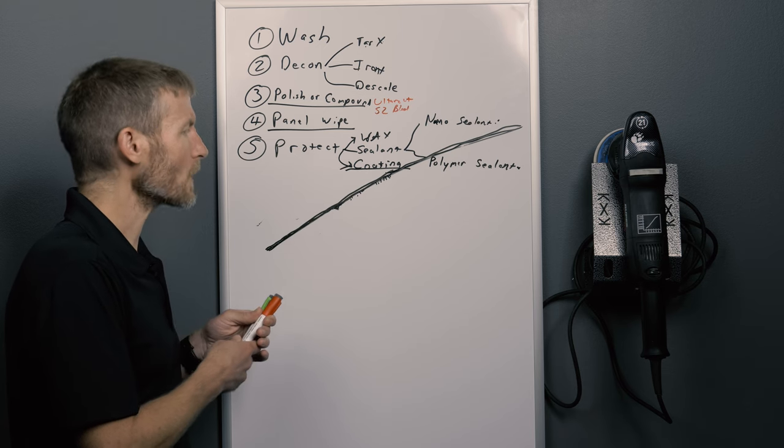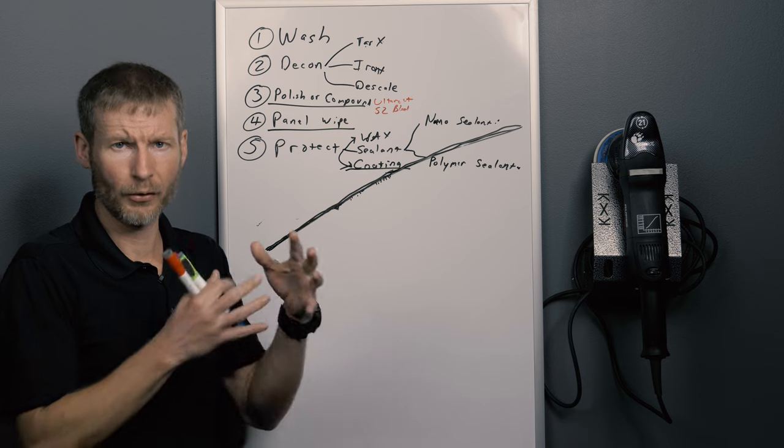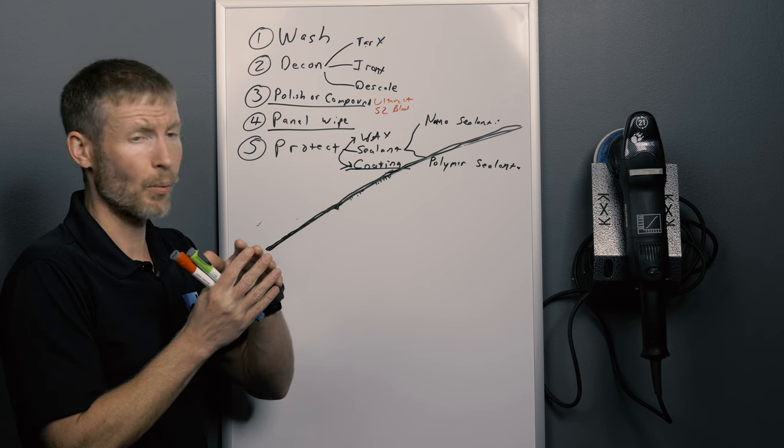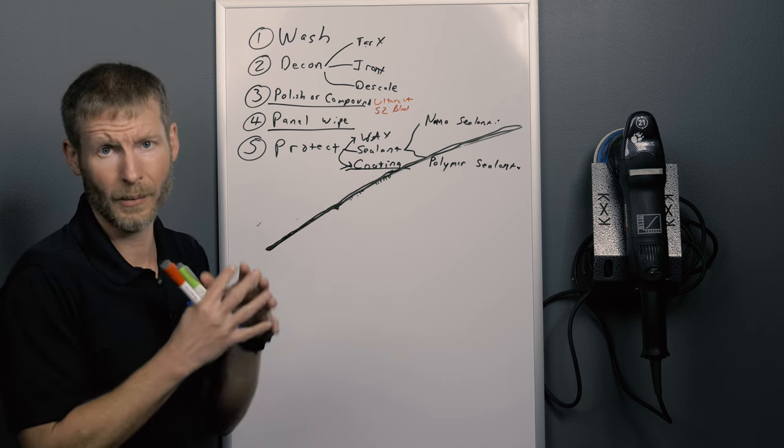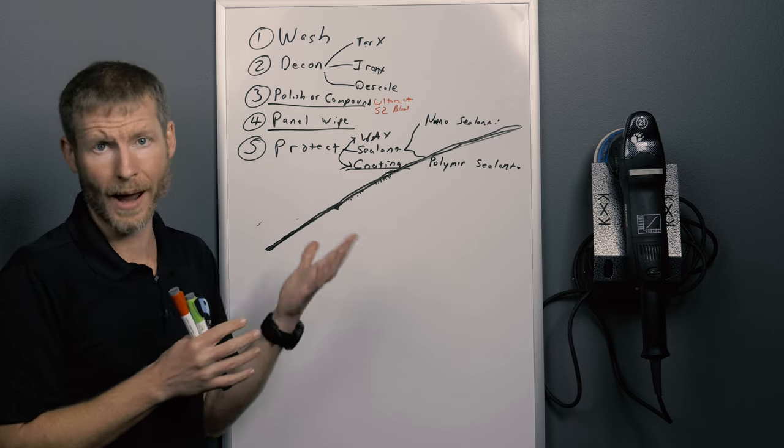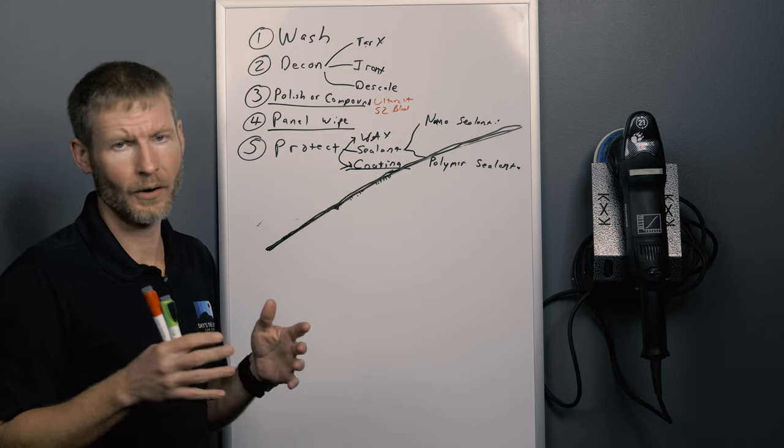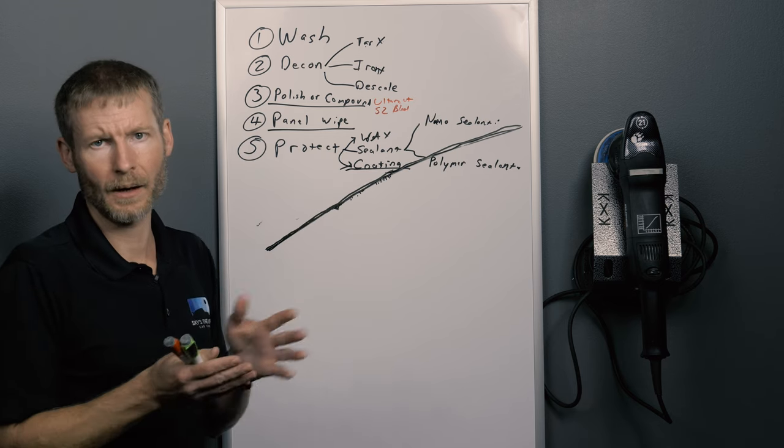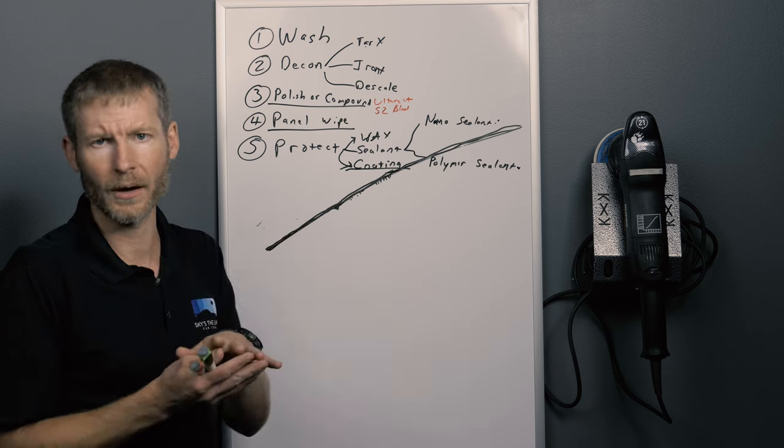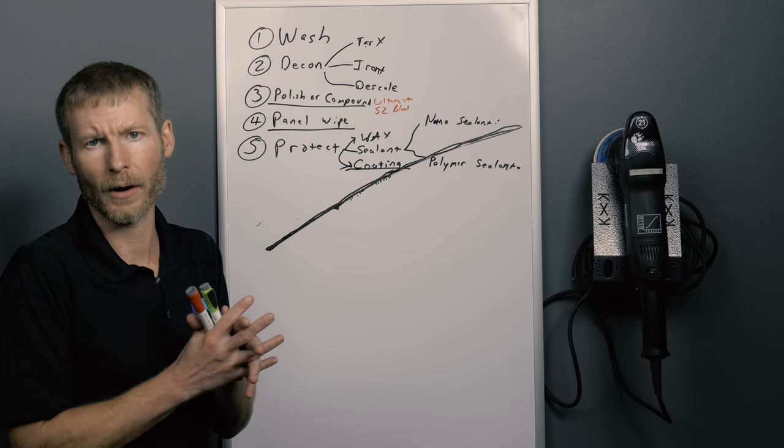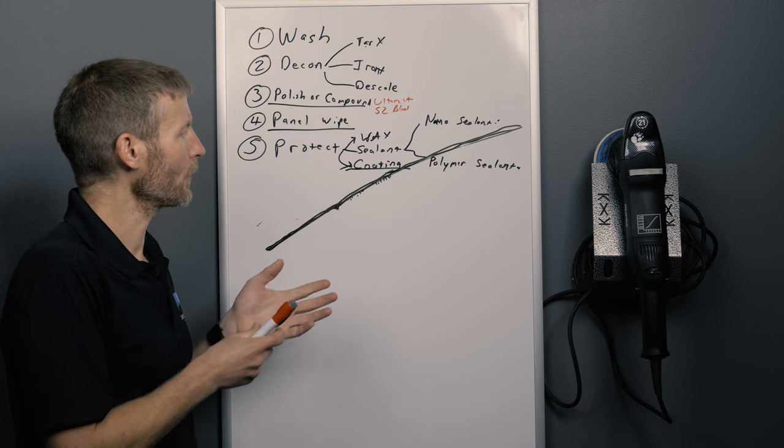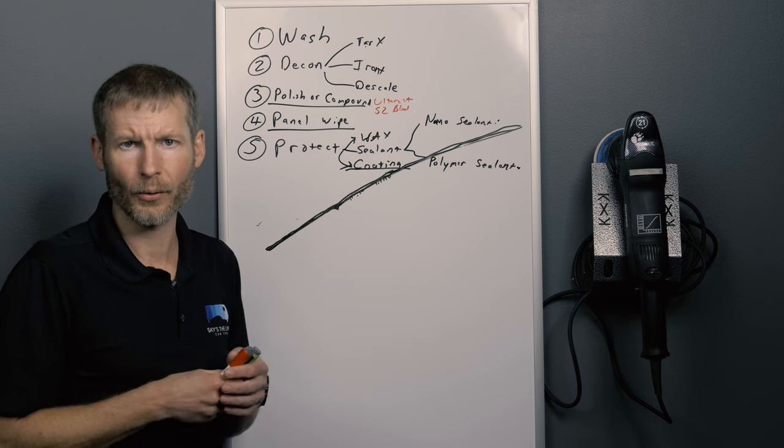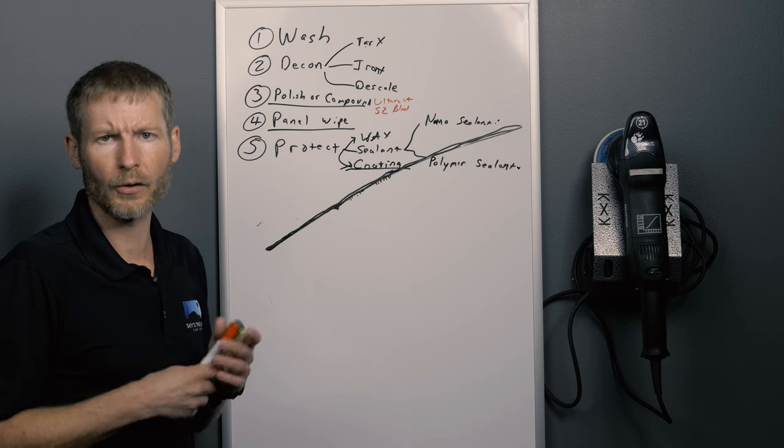So it's going to etch really, really bad and really easy. So over time, over 12 hours, 24 hours, especially if you IR cure it, it's going to become much more resistant and it's going to be a solid within 12 to 24 hours. Once it's a solid, then obviously it's going to be stronger. But it's still going to be those chains and the way that it's bonded to that paint is not going to be complete. In reality, it'll take weeks or months even for it to be at its full strength, at least weeks for it to be at its full strength. But it's going to be far stronger than a wax or a sealant pretty quick. Within three days, and this is, it all depends. Again, there's many variables in the world. The heat, the type of paint, the density of the paint, all the different things. If it's been in the sun, all these different things are going to affect how fast and how hard it cures. But after about three days, generally speaking, at this point you can wash it with soap. It's no problem.